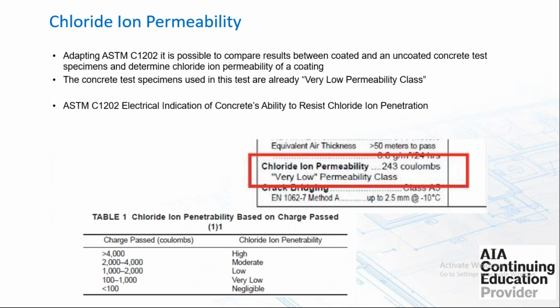Chloride ion permeability. This is a bit of a red herring in my mind and a waste of space, because the test is conducted on concrete, and concrete within the confines of this test, ASTM 1202, already has a very low chloride ion permeability. So when you see a test like this and a manufacturer claiming, oh, well, it has a low permeability class, it really means that, hey, the concrete was doing its job anyway without the coating.